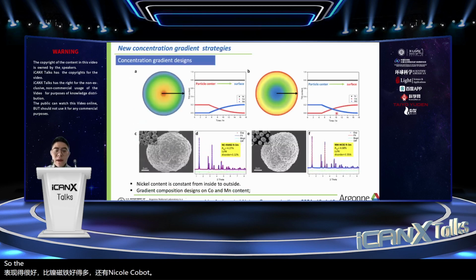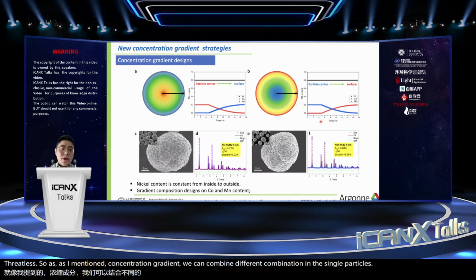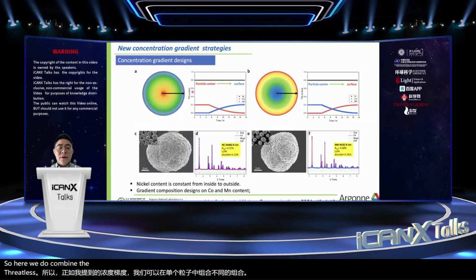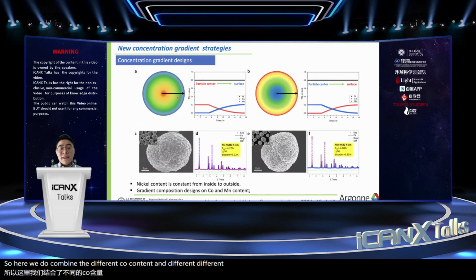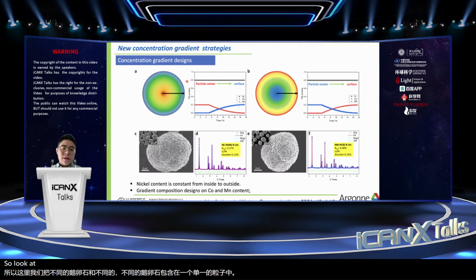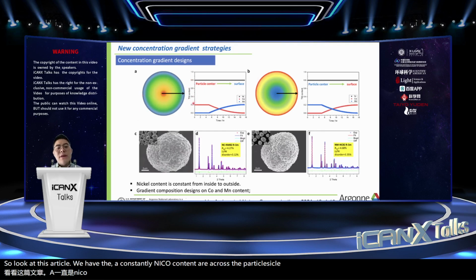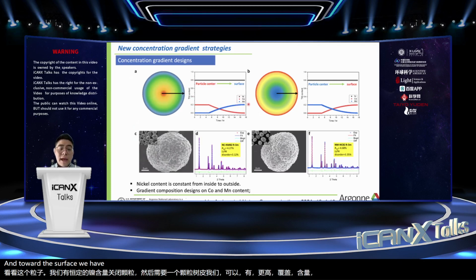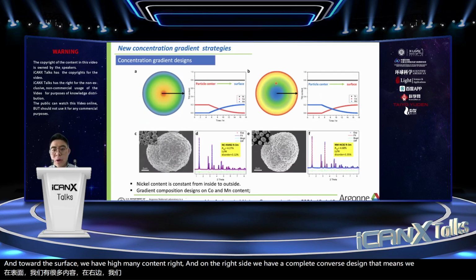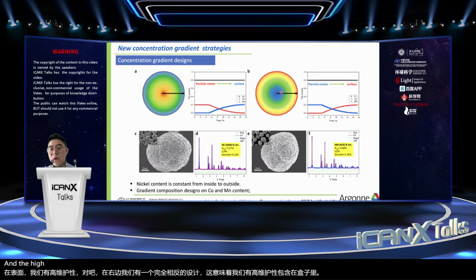So the next topic I would like to introduce is the new concentration gradient strategies. As I mentioned, with concentration gradient, we can combine different compositions in a single particle. So here we combine different cobalt content and different manganese content in one single particle. Look at this particle: we have a constant nickel content, and in the particle bulk we have a higher cobalt content, and toward the surface we have high manganese content, right? And on the right side, we have a completely converse design. That means we have a high manganese content in the bulk and a high cobalt content at the surface.